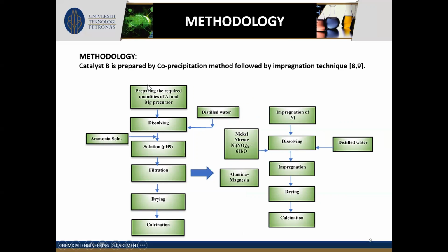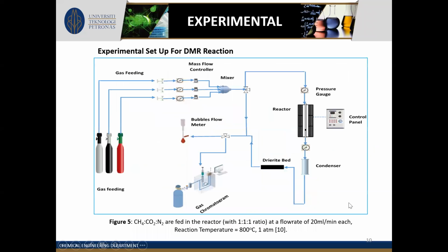For methodology two, we prepare catalyst B by co-precipitation followed by impregnation. Here we prepare the catalyst support, that is alumina and magnesia, by a similar methodology as I discussed previously. Further, in the second step, we add nickel nitrate salt to the prepared catalyst support, and we do the same procedure again to prepare catalyst B.